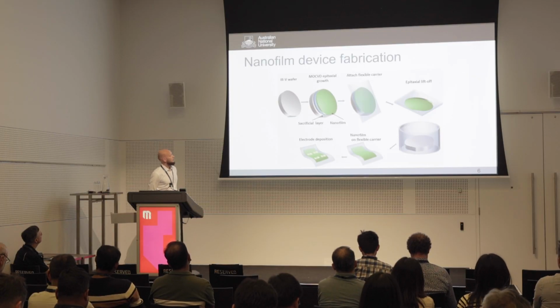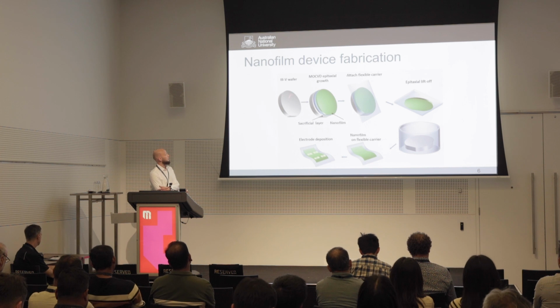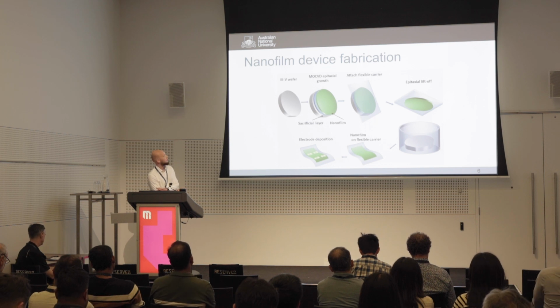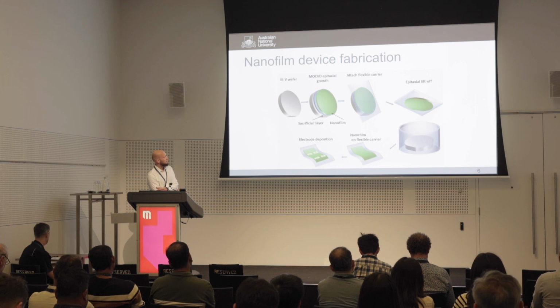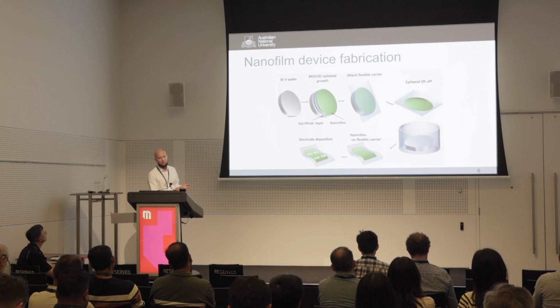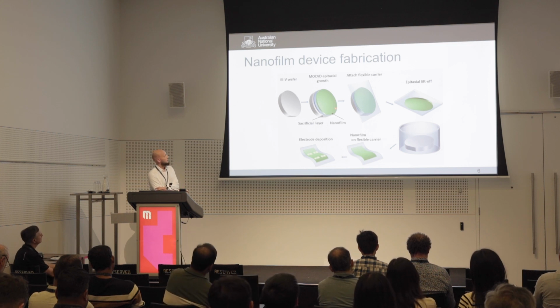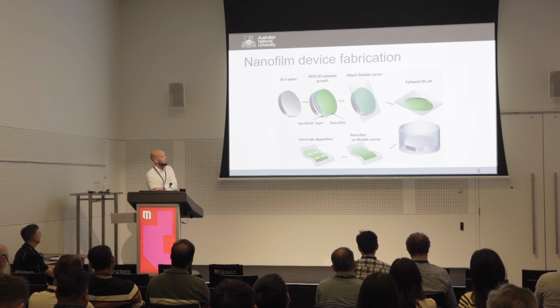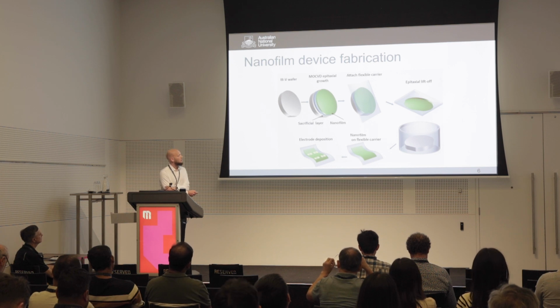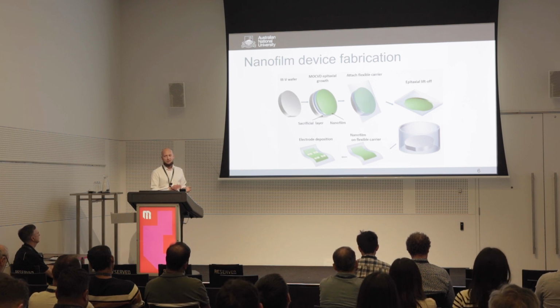This is how we fabricate the nanofilms. So we start with a III-V semiconductor wafer, then we take it to ANFF ACT node to do epitaxial growth using a tool called MOCVD. First layer we deposit is sacrificial layer, and on top of that we deposit the actual nanofilm, which we will use as a device. We attach a flexible carrier on top, and then we do a chemical process which removes only the sacrificial layer and peels off the nanofilm.